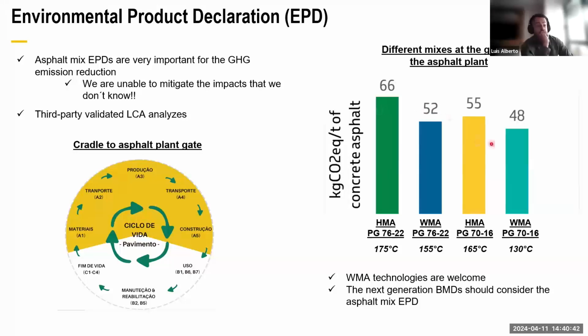One point I would like to call your attention to is that when you compare the warm mix asphalt with a typical binder to the mix with modified binder, there seems to be a huge difference in the production temperature. We got a very different impact for this mixture. It is around 40% higher when compared to the warm mix one. So when you do all the balance, we need to think about the thickness reduction, and whether the durability is enough to give us a more sustainable pavement. This is something that we need to think about. So the point I would like to make here is that warm mix asphalt technologies are more than welcome on this journey to reduce the carbon footprint.